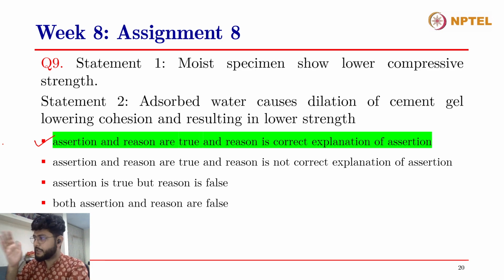So this is a very interesting question, because when we come across the Indian standards, we see that the Indian standards recommend for the tests to be carried out within, let's say, 2 hours after you have taken out the specimens from the curing tank, and the specimens must be air dried only, not heated up, must be dried in ambient air conditions, and the surface only should be dry, not the core of concrete. So it should be in an SSD condition, right? So this is exactly why we want to carry out a strength test in an SSD condition, so that we'll have consistent results. We will not have the effect of saturation,